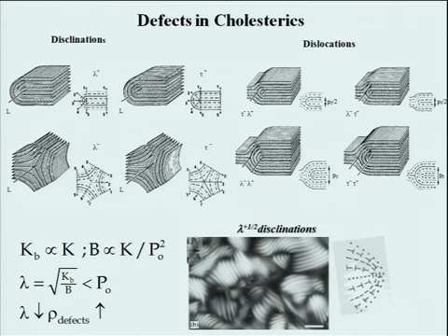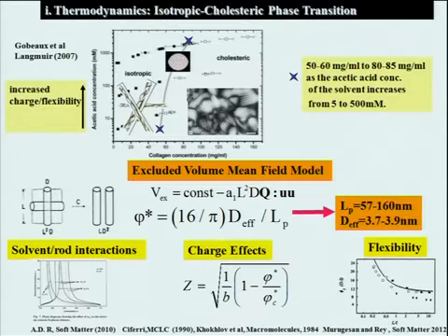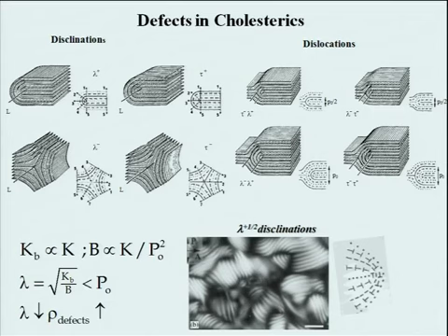So the other point is, okay, so this is the texture, you have some topological defects. Does it follow topological defect physics of synthetic liquid crystals? So here are some of the disclinations and dislocations observed, typically described in terms of lambda lines, which are, the core of these lines are non-singular, so they are energetically less costly than these tau lines that are singular.